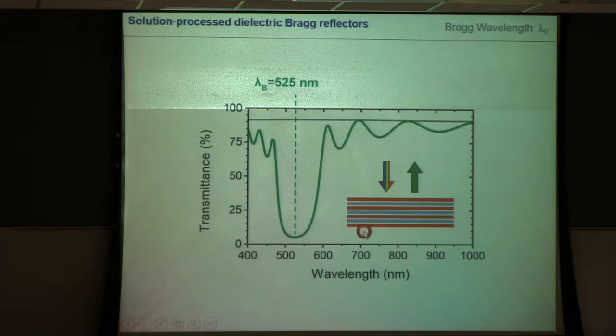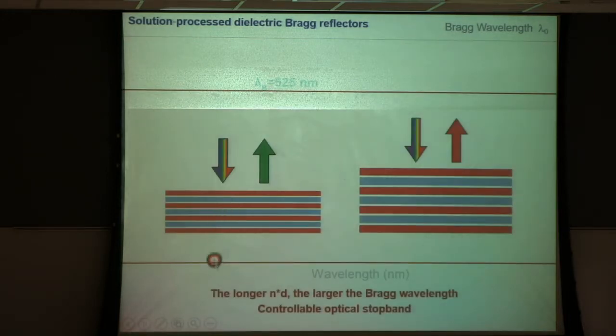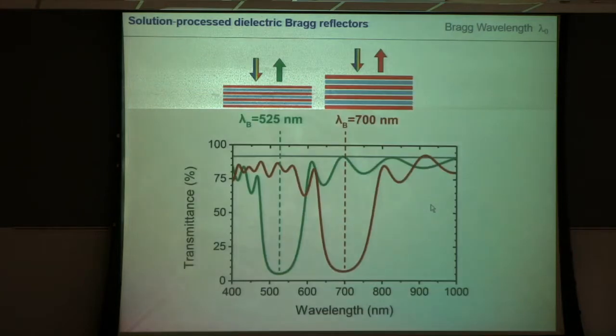How do we decide that? With the thicknesses of those layers. Indeed, the Bragg wavelength essentially depends on the refractive index of the layer and the thickness. So one way to change the Bragg wavelength is really just changing d down here. So then you go to thicker layers, you change n times d, and that means you shift it to a higher wavelength. We did that here, so we started first with a mirror with 525 nanometers Bragg wavelength, and once we increased the layer, 700 nanometers.